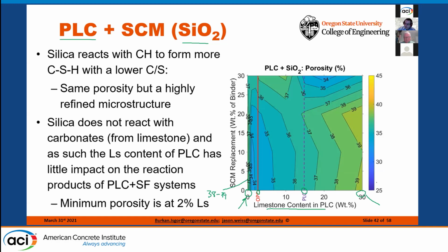Now, if we look over on this bar on the right-hand side, it's just a color-coded map of high porosity, which is yellow. This is our classic clinker system. And if we get down to really low porosity, we get into these blue ranges. Not surprisingly, as we add a little bit of limestone, as we've seen, the porosity decreases, and then the porosity starts to go back up. But at all of these points here, we're only at about 37% porosity, where if we used our clinker, we're at about 39% porosity. So everything is slightly lower than what we had originally.